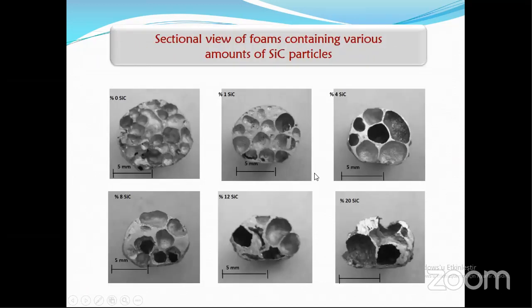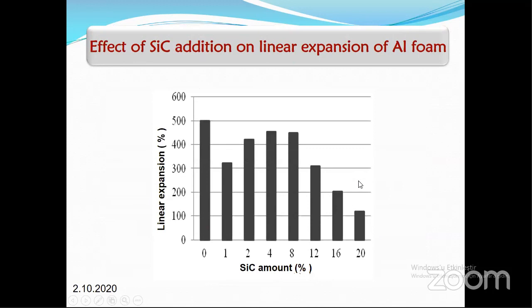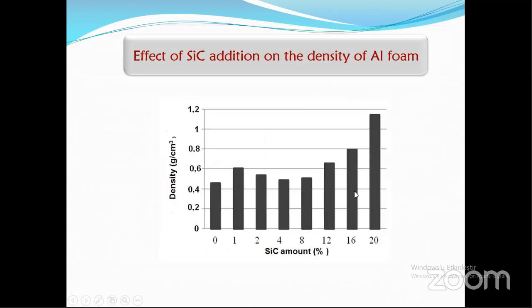This is the cross-sectional area of the sample containing various amounts of silicon carbide particles. This is 0, this is 1%, 4%, and 8%. After 8%, the structure is not good. Just in order to show you, I kept this one. This is the linear expansion rate of aluminum foam. The 0% goes to 500%. When we add 1% silicon carbide, it is just over 300%, 2% over 400%, and 4 and 8 about 450%. And then because of the collapsing, it starts decreasing.